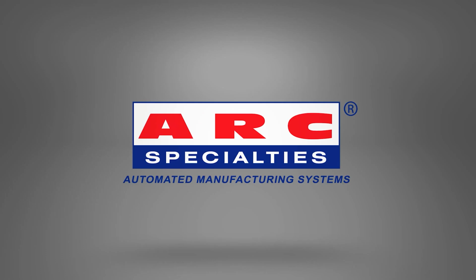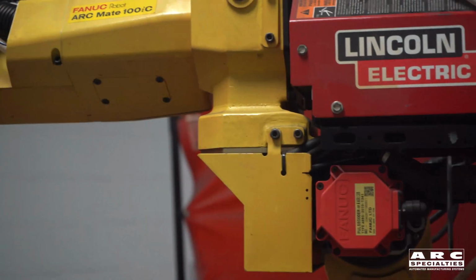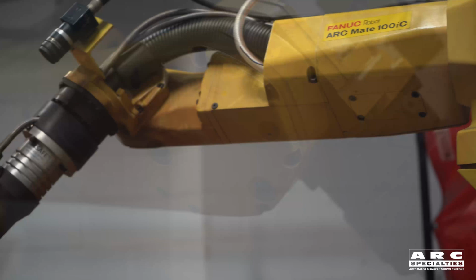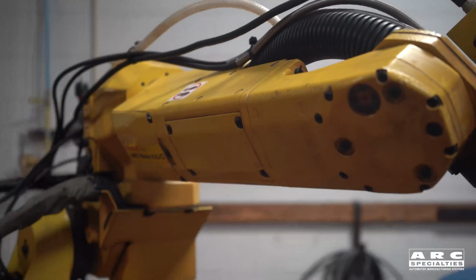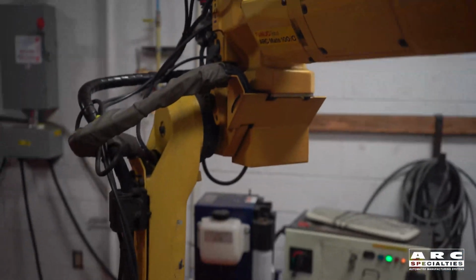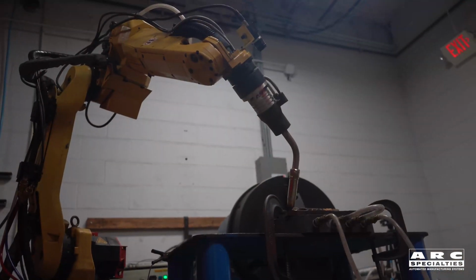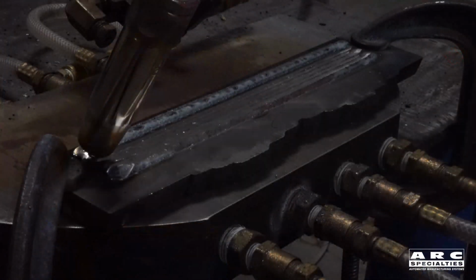In this case, we've decided that we want to use a FANUC robot, a Lincoln pulsed MIG power supply, and a very high strength wire. This is 140 KSI tensile strength wire. That's about the upper limit of welding wires. And with this process, we're trying to make some samples for material property testing.